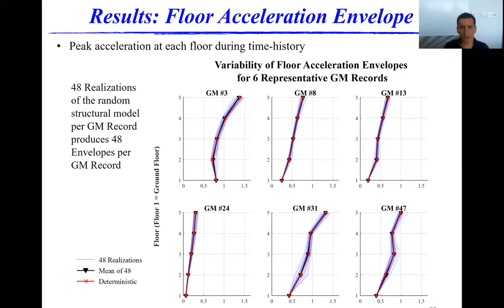So here I've plotted 6 representative ground motion specific PFA envelopes of the 50 total. So for example, ground motion 3 is subjected to 48 structures. So the 48 different envelopes that were a result of those 48 analyses are pictured here in blue. The mean of those 48 is this black line here, and the red one is the result from the deterministic model case where the mean model parameters were used. And we can see that they align well, which corresponds with the assumption of a first order approximation.